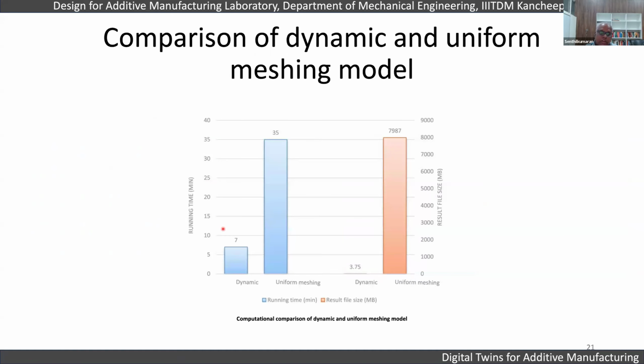Right, so you can see that when you use dynamic versus uniform, the running time for a simple case, and also its file size, is shown here. You can see that if you use dynamic, the file size comes down from 7.9 GB to 3.75 MB. So it has reduced to 3.75 MB from 7.9 GB. The file size got reduced. And also you can see the total running time of the simulation came down almost 5 times, right? So 35 to 7.